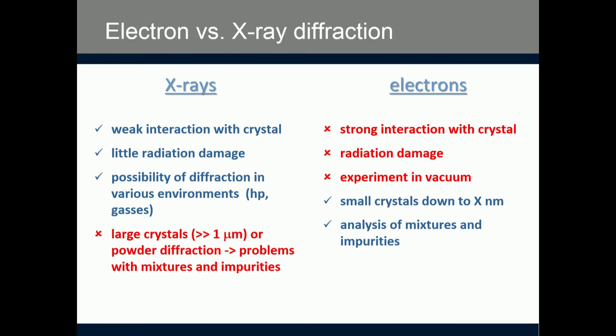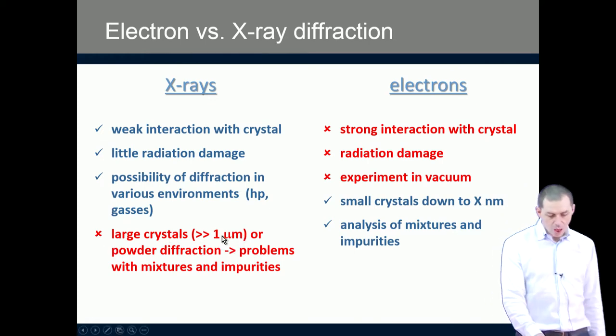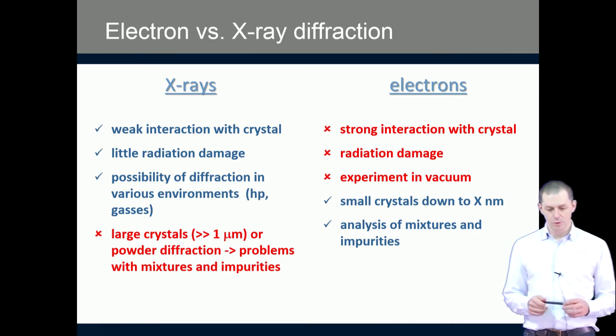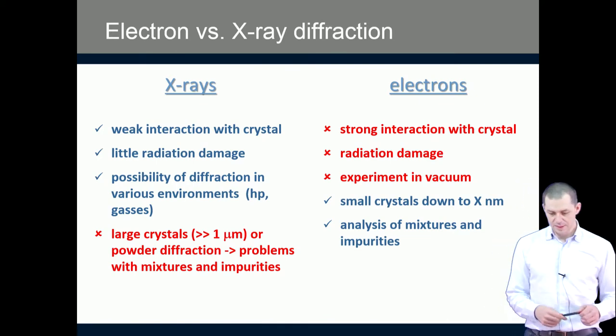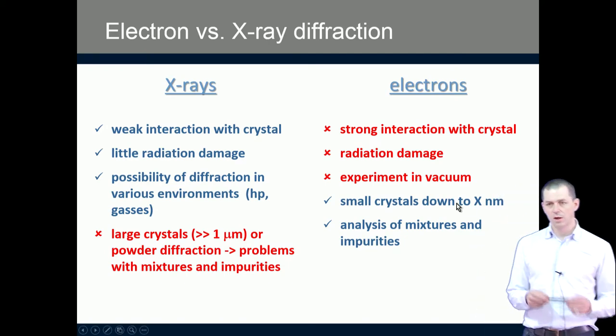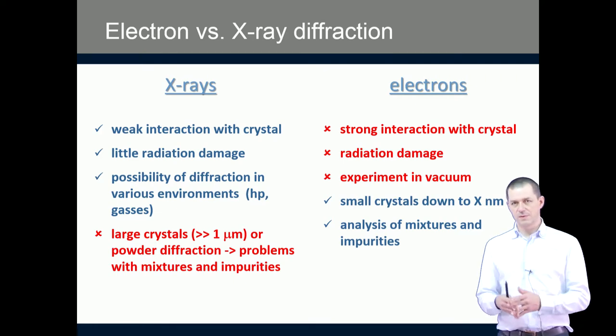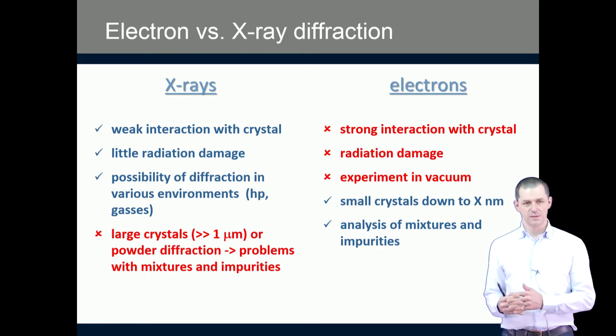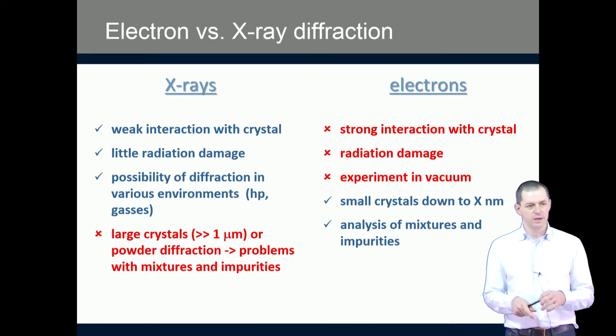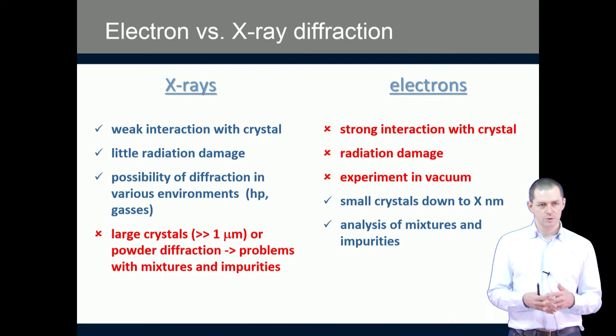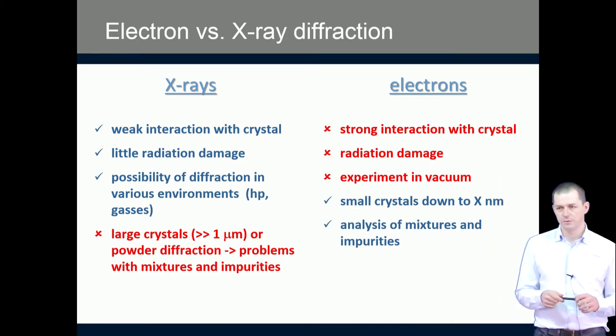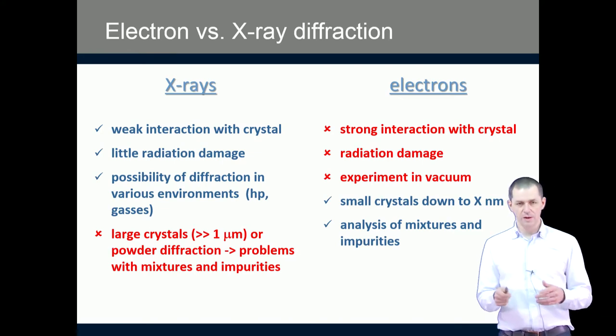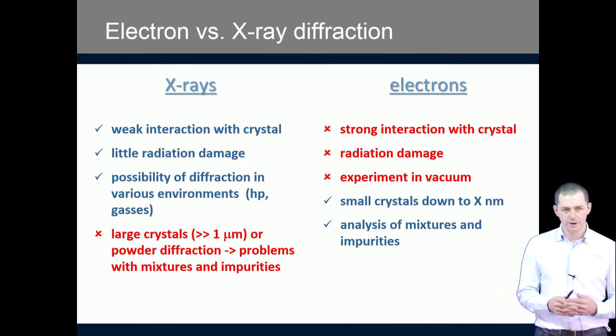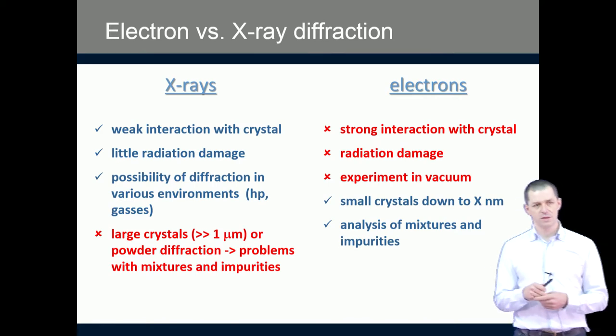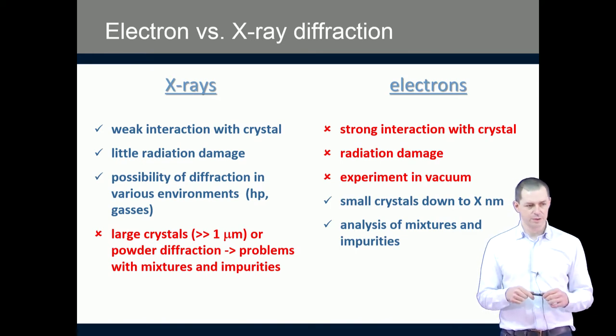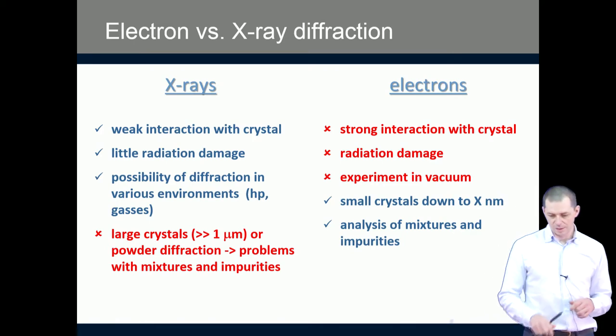On the other hand, X-rays require large crystals, so much larger than one micron, or you need to use powder diffraction with all the problems of mixtures of phases, impurities, and peak overlap. Electrons can measure small crystals down to a couple of nanometers, and therefore you can easily analyze mixtures of phases. Well, if I say easily, it may still be complicated, but if you have a mix of phases in the electron microscope, you can find single crystals, individual crystals of different phases, and measure each of them separately, while in the powder pattern you have an overlap of all of them, and it may be very difficult already to identify that you have a mixture of phases, not to speak about the separation, indexing, and possibly structure determination from such a pattern that contains a phase mixture.